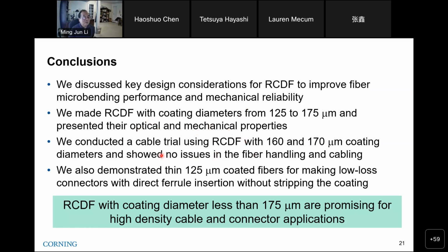Our cable trial shows that the RCDF could be cabled with no issues. And finally, we show that 125 micron coated fiber can be used for making connectors without stripping the coating. So we believe the reduced coating diameter fiber, with a diameter less than 175, is promising for high density cable and the